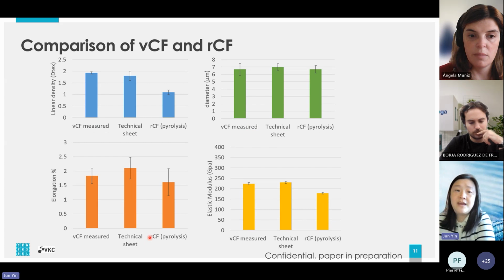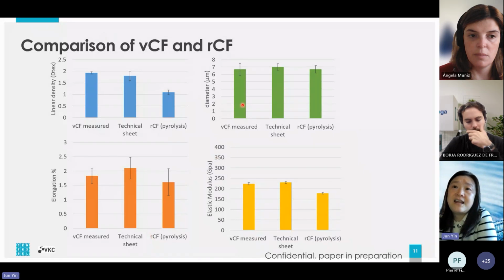So here you can see the result. Again, we compare the linear density, the diameter, elongation, and elastic modulus. We can first compare the virgin fiber we measured by our method with the technical sheet we received from the product producer. And we can see all these parameters are comparable. So that means our method makes sense.